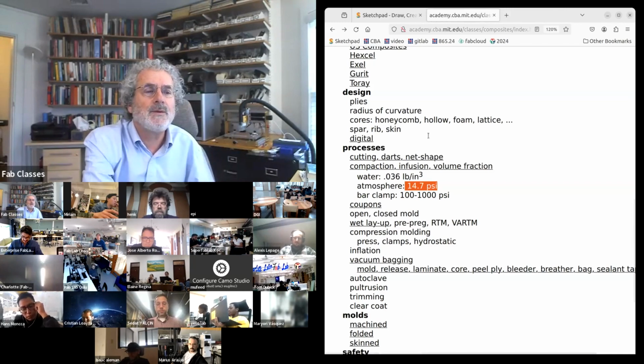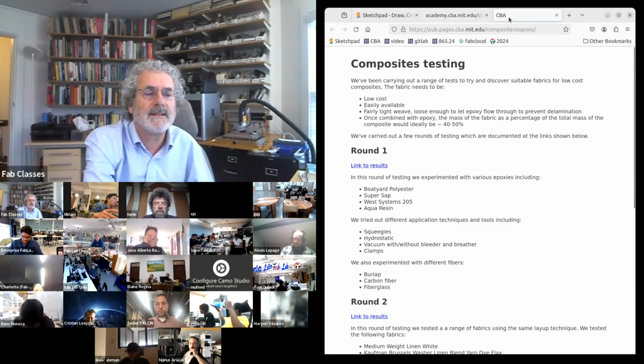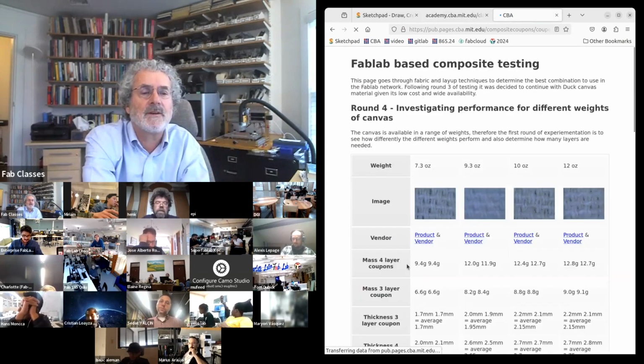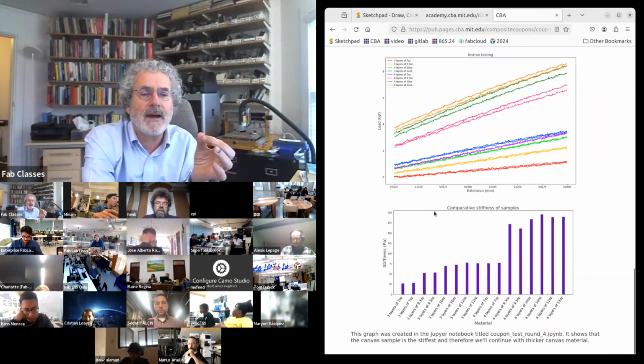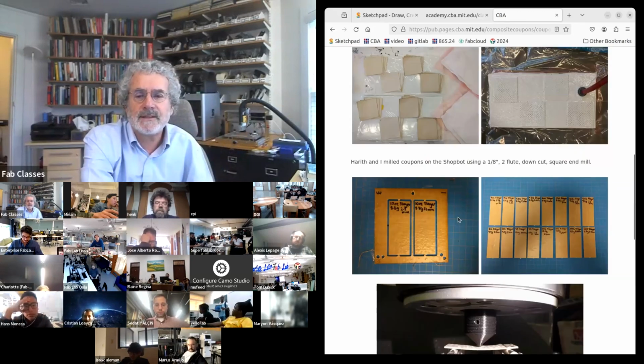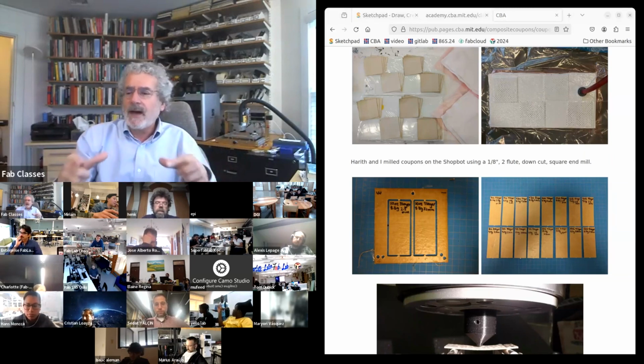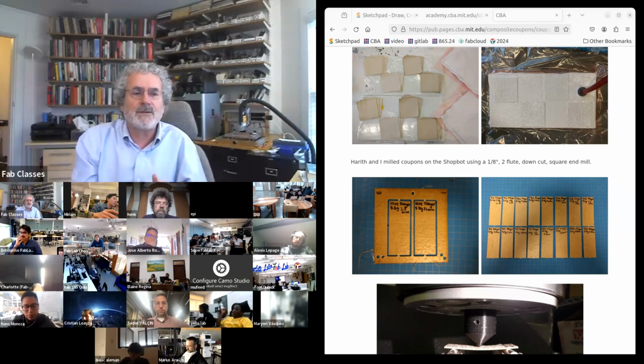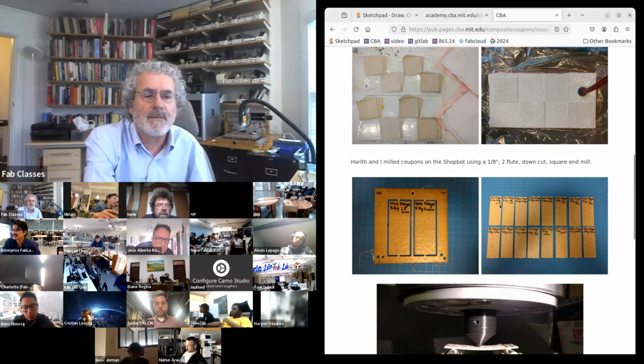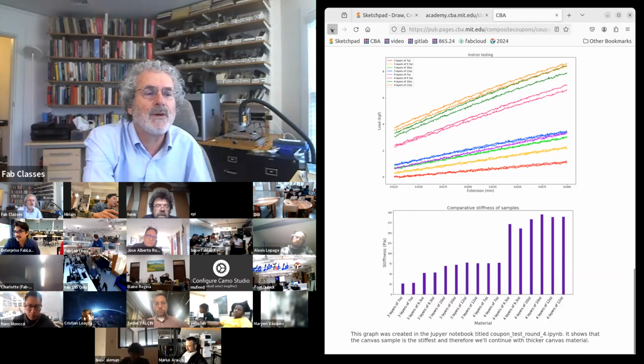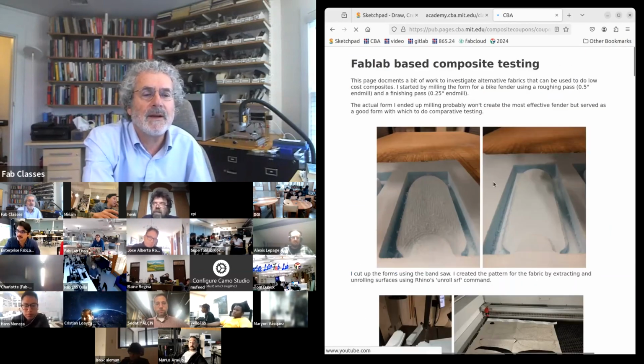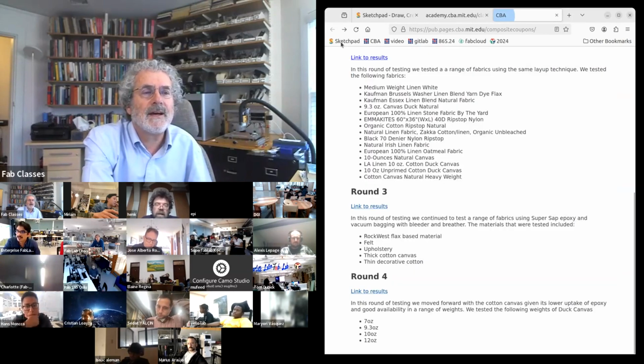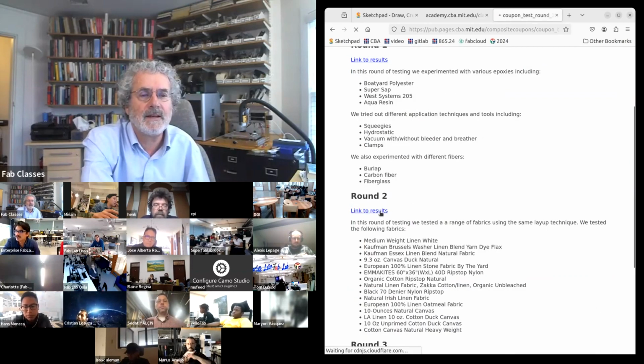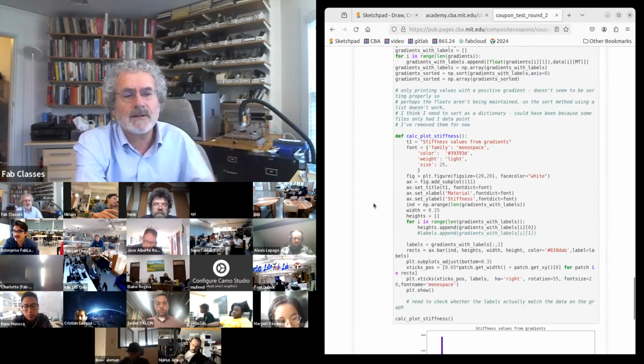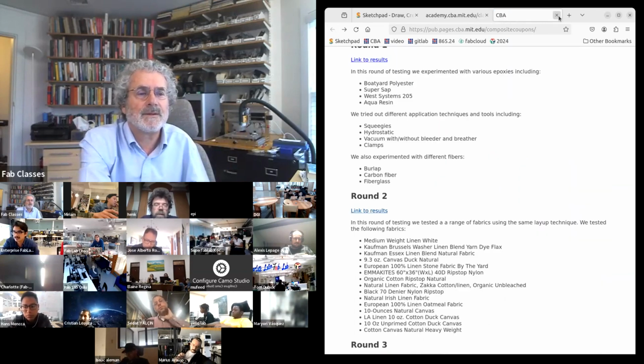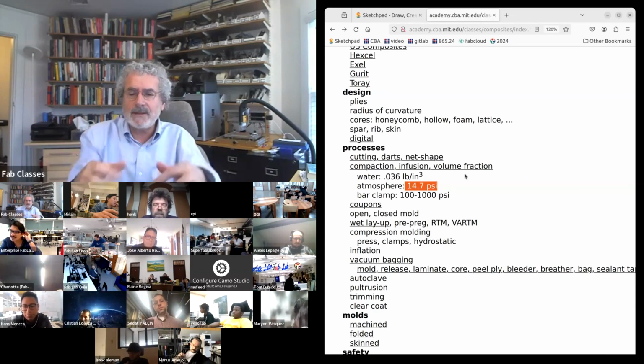Now, this term I've been using, coupons. A coupon is a test composite. And this was a series of tests we did of different materials. A coupon is you make a strip out of the composite and you use it to test the process. So when you're learning about composites, before you spend a lot of time with your mold, start by making just simple rectangular strips to test your fiber and your compaction. What came out of these tests, for example, is we found how good linen is. We compared a number of different materials, and it showed that linen has surprisingly good properties to make friendly composites. This is linked to analyzing lots of different materials using one of those material testers I showed you before. So if you're going to start composites, make little test coupons.